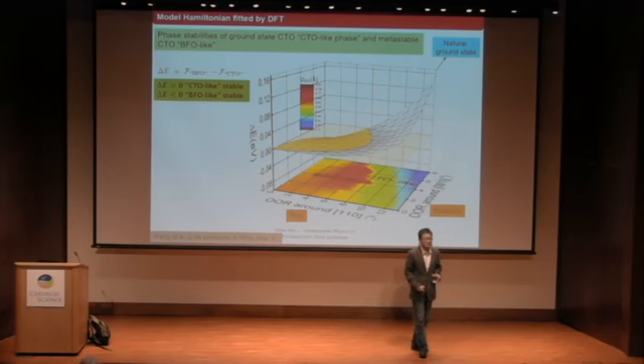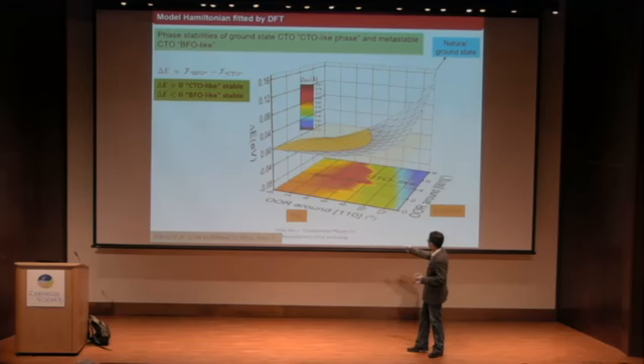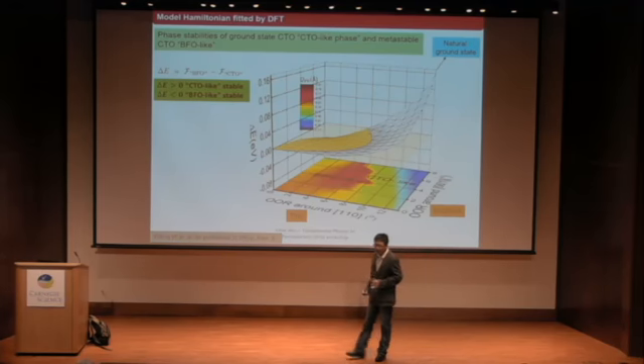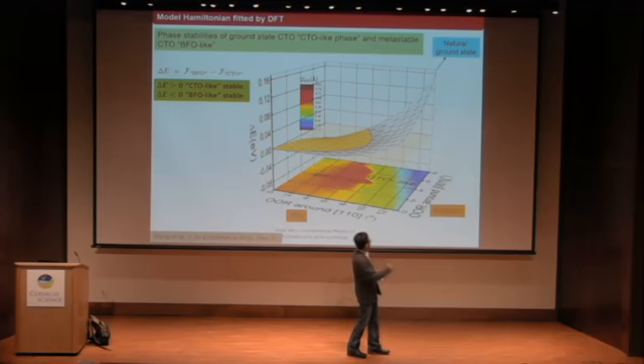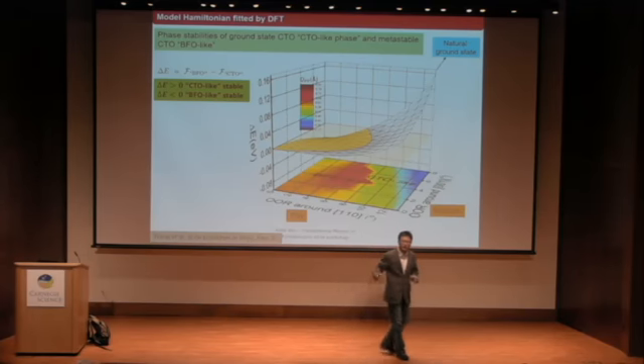You can see that when the rotation angle and tilting angle are fixed at experimental values around 12 and 8, you recover the DFT ground state.